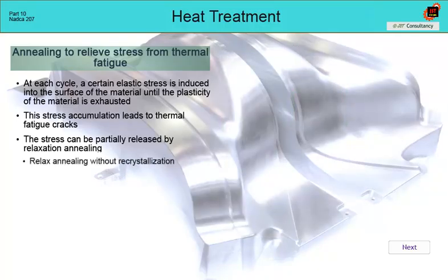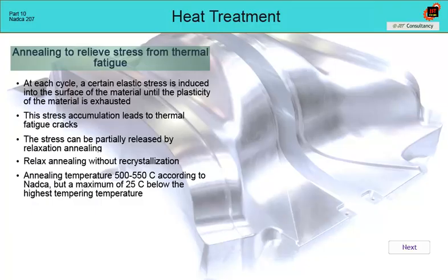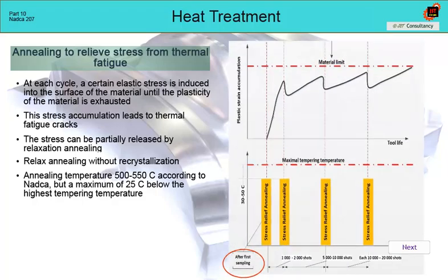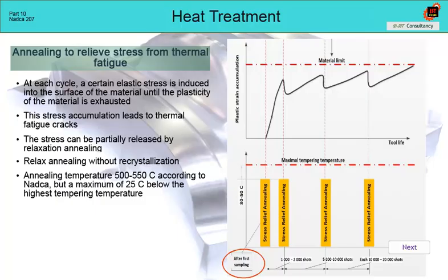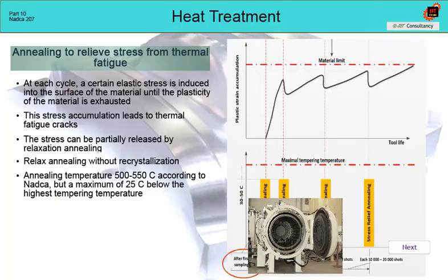Annealing is without recrystallization. At a temperature of 500 to 550 Celsius, the highest permissible temperature is then 25 Celsius below the highest temperature of the previous tempering. The first annealing process should be included immediately after sampling, before the die is delivered to the customer. Since it is working in finished dies, it must be done in a vacuum or under a protective atmosphere.